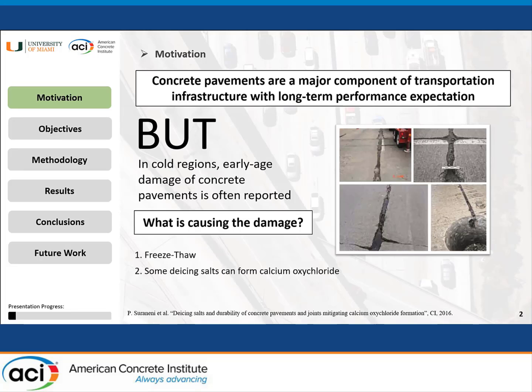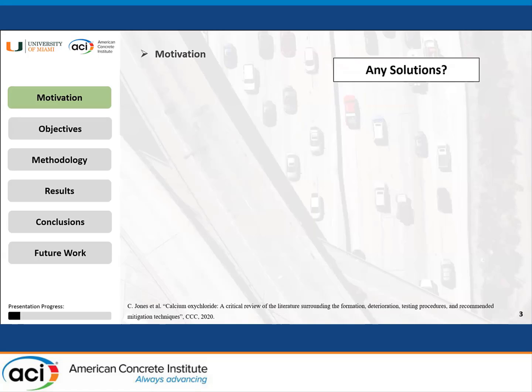In addition to that, we use de-icing salts, which can form calcium oxychloride while interacting with calcium hydroxide, which is in the hydrated concrete. Calcium oxychloride is an expansive chemical, which also leads to internal pressure, which can also lead to cracks and deterioration of our concrete pavement. But are there any solutions to prevent this damage?